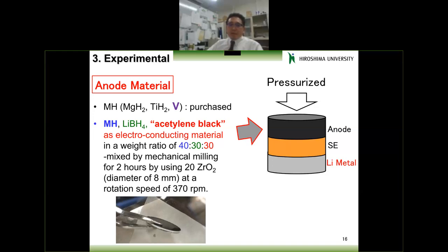Of course, this hydride, so-called MH, is the anode material. Of course, these are purchased. Then this MH, lithium borohydride, and an electroconducting material, carbon black, so-called acetylene black, were mixed by ball milling. The weight ratio is 40-30-30 for MH, lithium borohydride, and acetylene black.